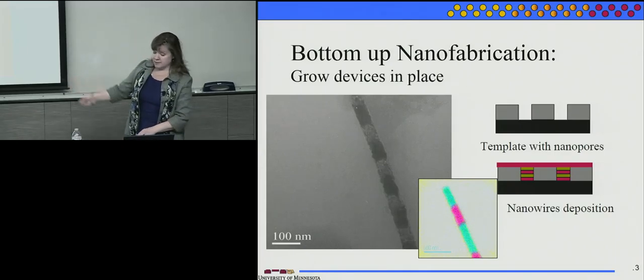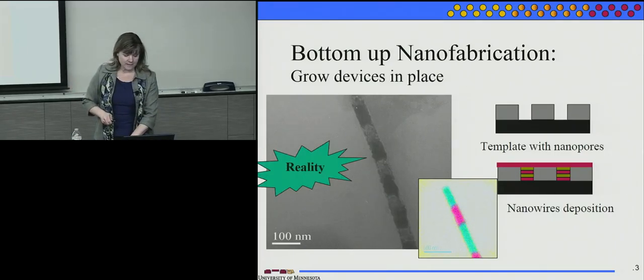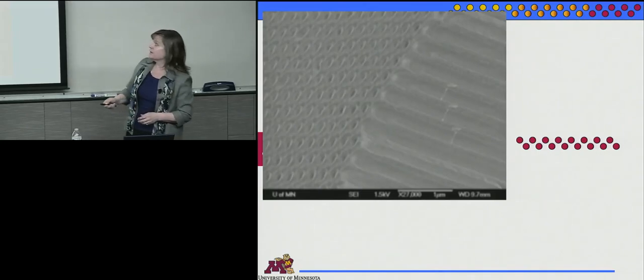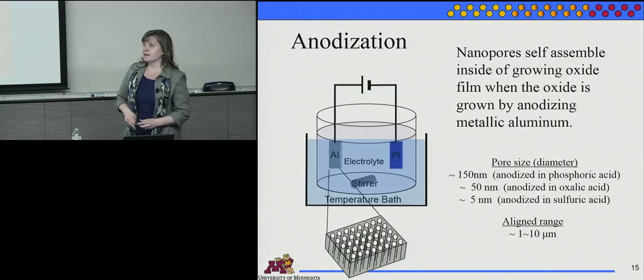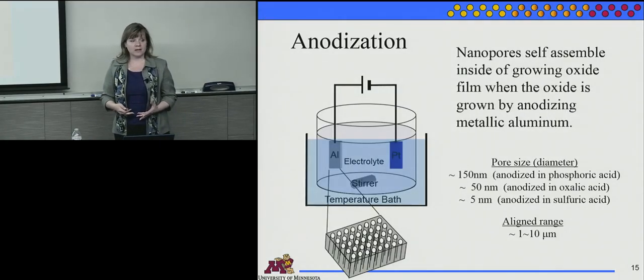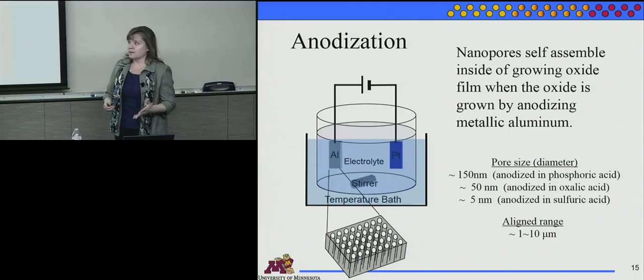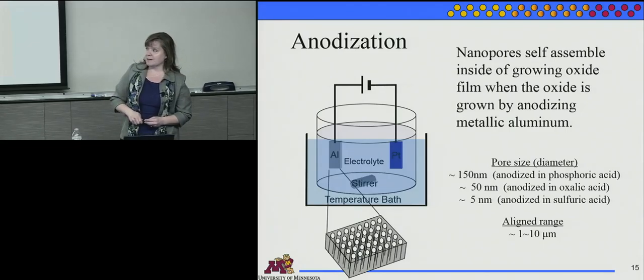And that's an X-ray map, so you can see the compositions there. And we'll go through different wires where they're still in the oxide, so they're not damaged, and then they have very smooth sidewalls. So it's always challenging to try to get a zoom up of the sidewalls. I think if you look on the sides, it's a little better, but they really are very smooth aluminum oxide, and then the metal grows inside there. It has a conformal coating, so you end up getting sidewalls that mimic what you see in the oxide.